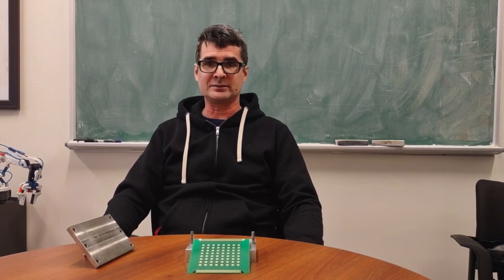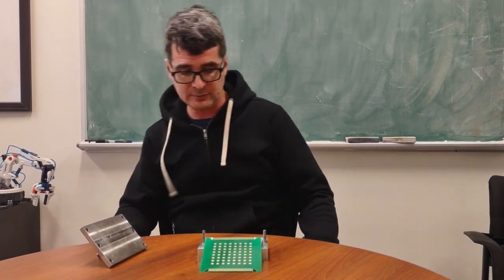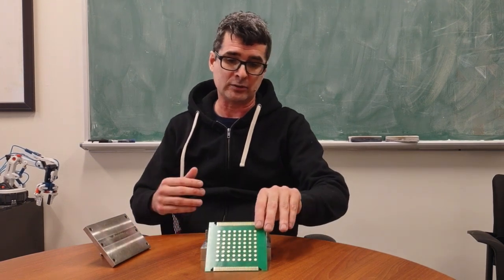So this is a strength of my group at McGill. In this paper, the lead authors, Alex Abad and Nushin Zanali, made over 200 different materials, so 57 different dopants, and they were synthesized at 3 different synthesis temperatures. And what they found is a lot of the materials were single phase, which is very encouraging, so we did X-ray diffraction.